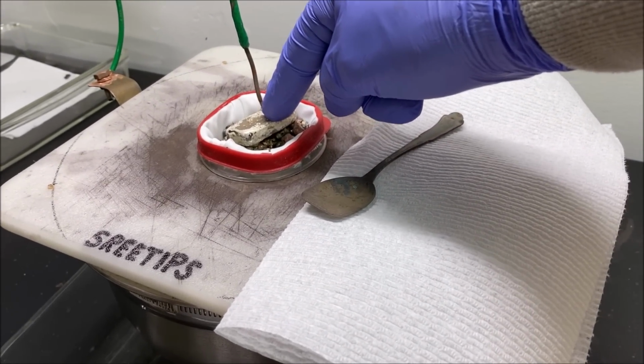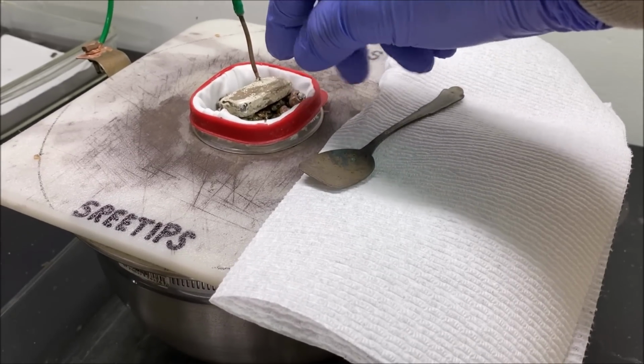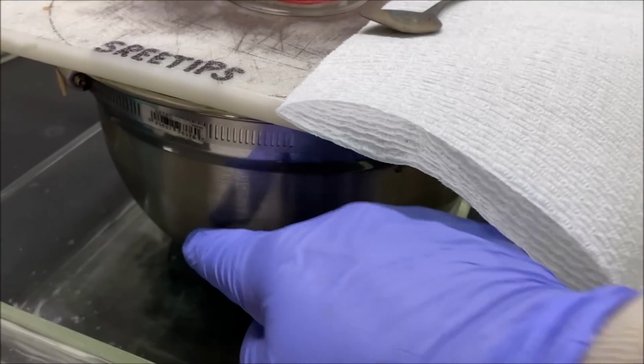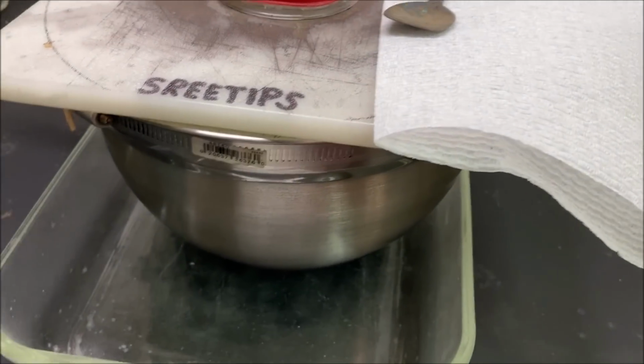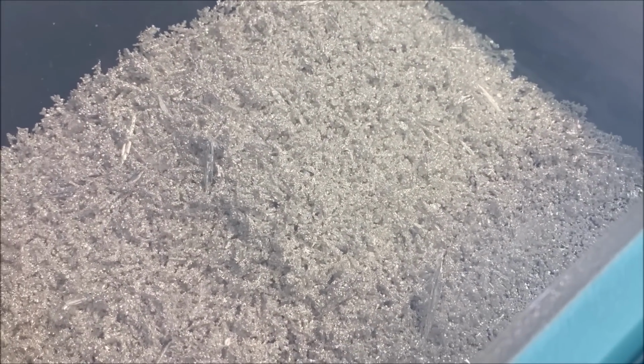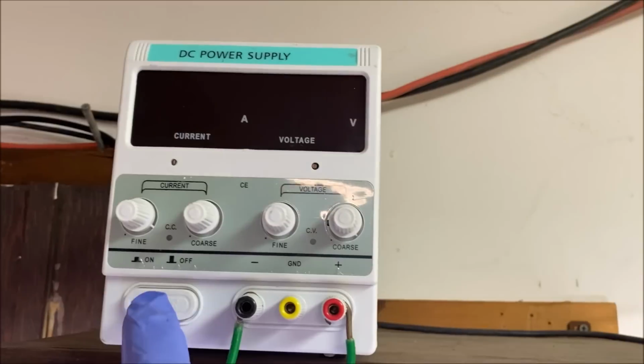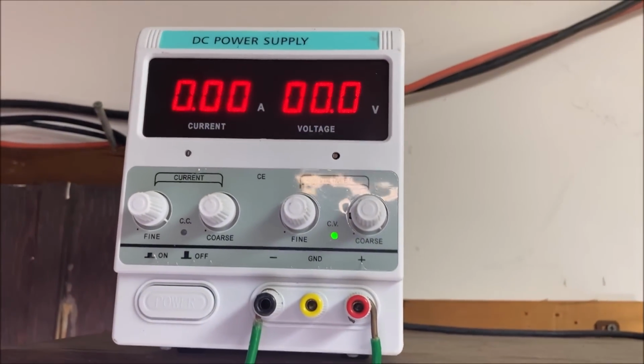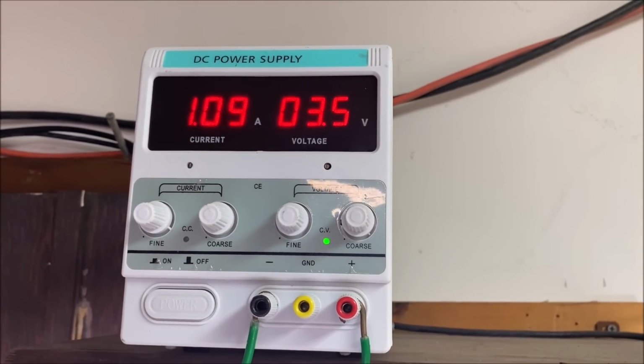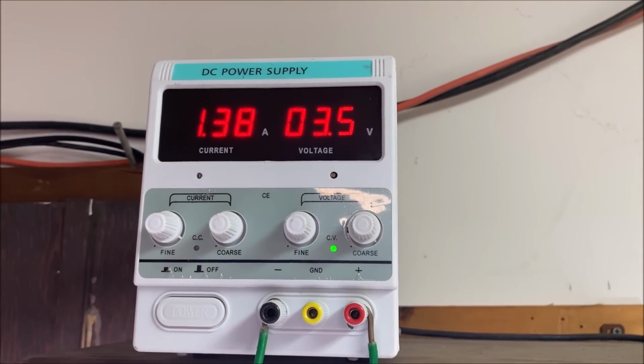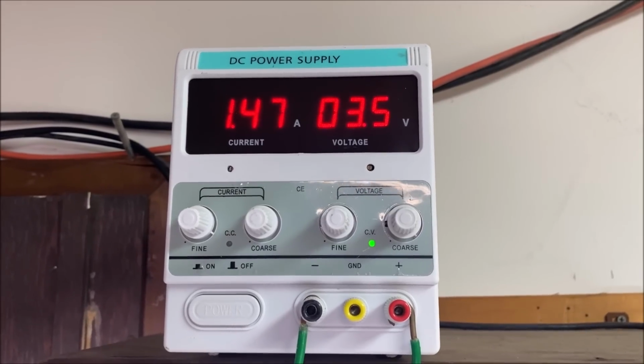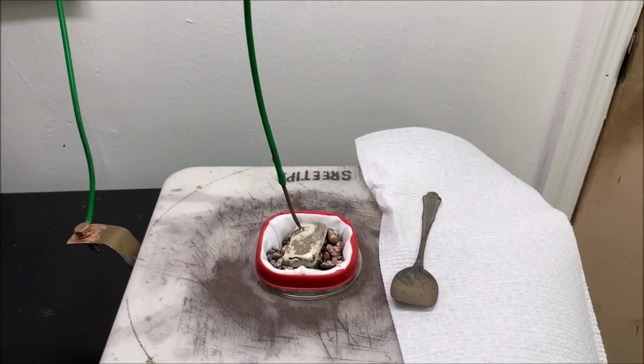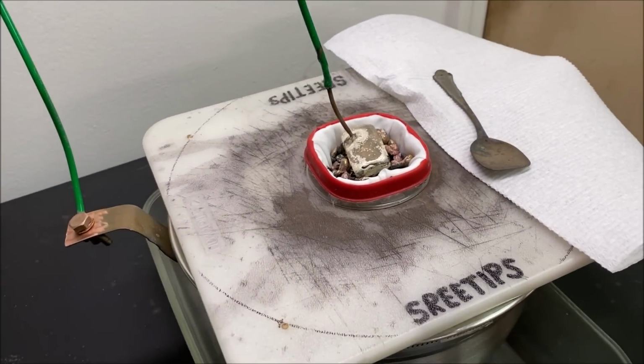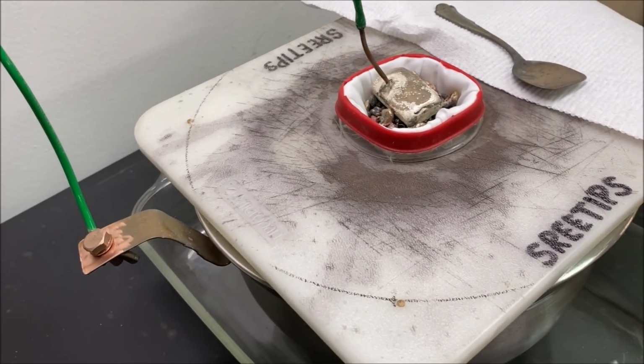We pass a current through this impure silver. It dissolves the silver. The silver passes down through the electrolyte and plates out on the inside of this stainless bowl as absolutely high purity silver, just like you see here. So let's go ahead and energize this now. We run this thing at 3.5 volts DC, and you can see the amperage is climbing there as the electrolyte finds its way through that filter and comes in contact with the impure silver.